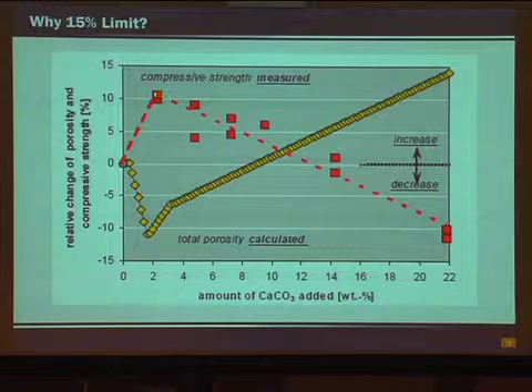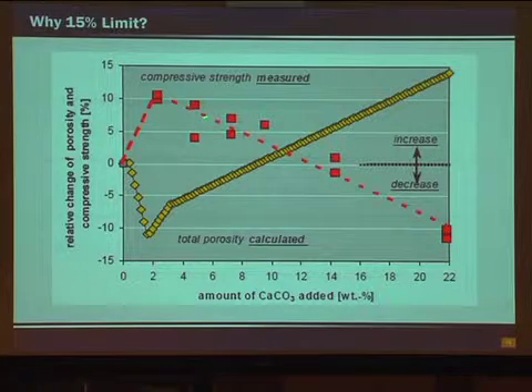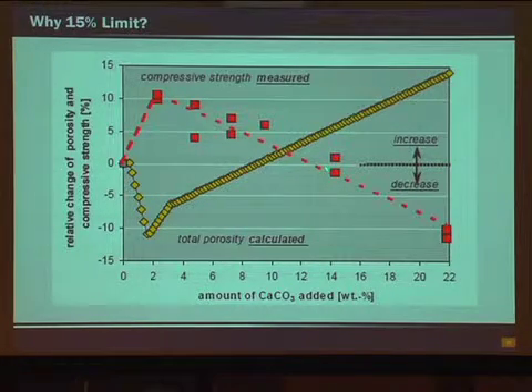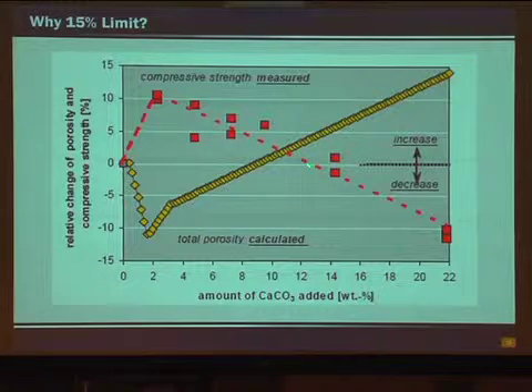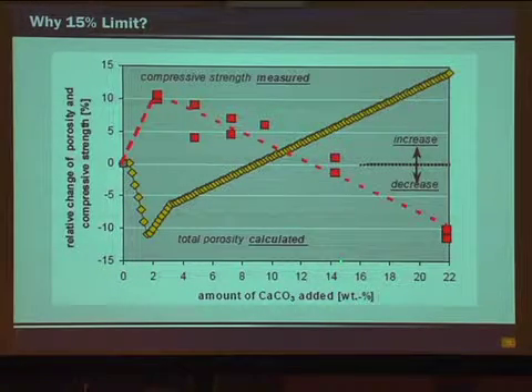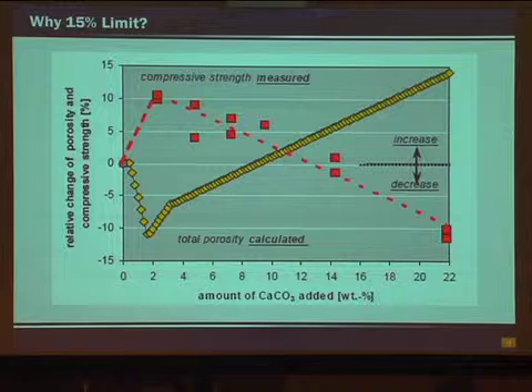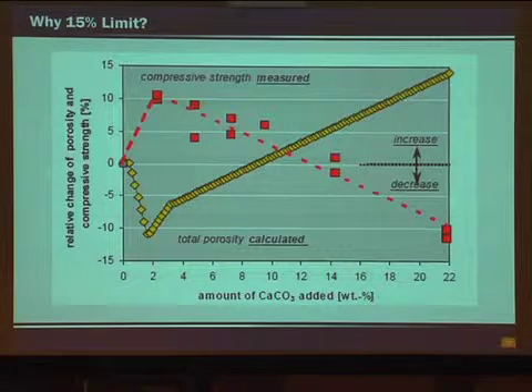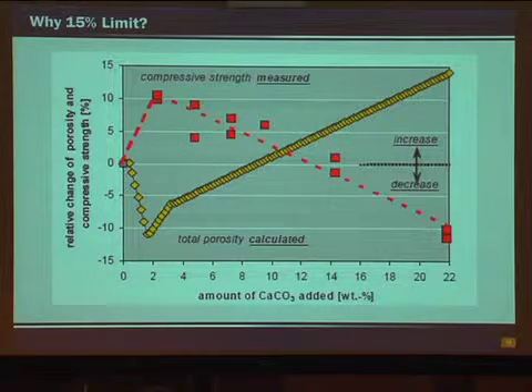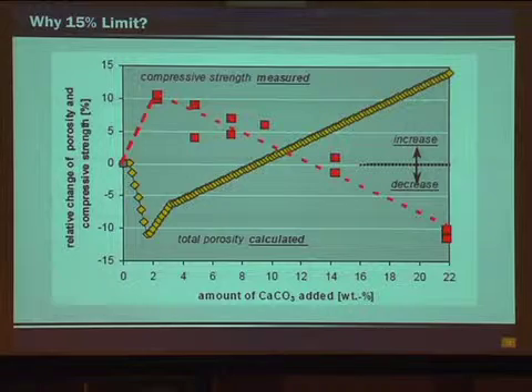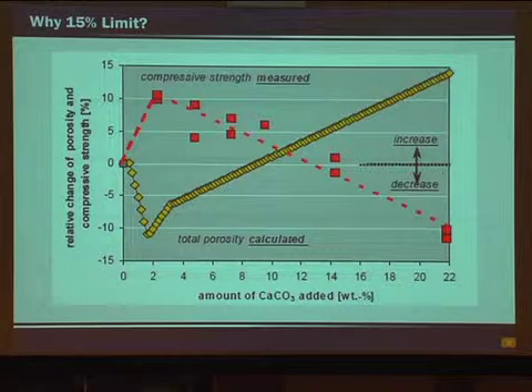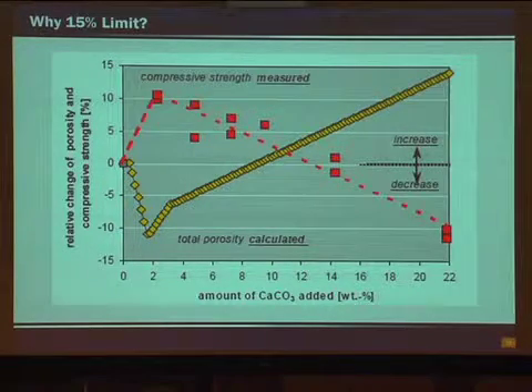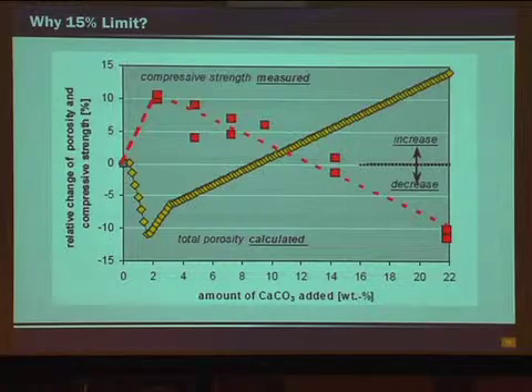Well, that gives us a benefit of now adding more and more limestone until we basically get back to a zero relative change. And so that happens to be about 14-15% limestone addition. So that is where that spec limit basically comes from, is this data right here showing that we could put up to about 15% and not have a significant impact on strength.